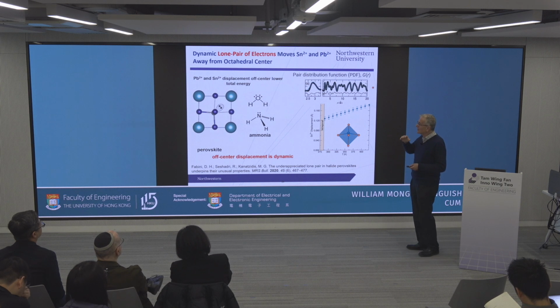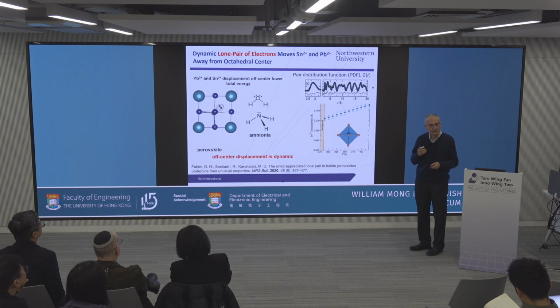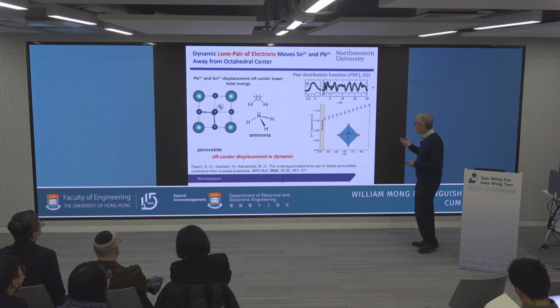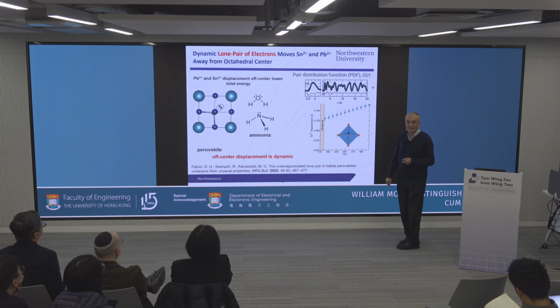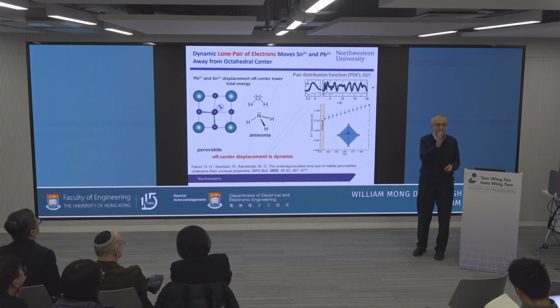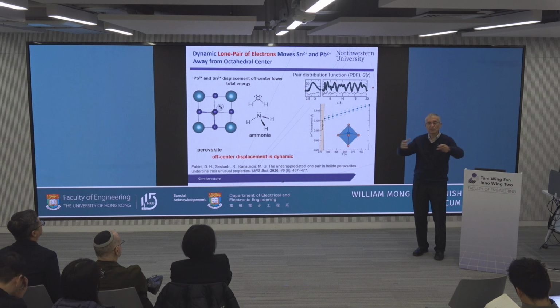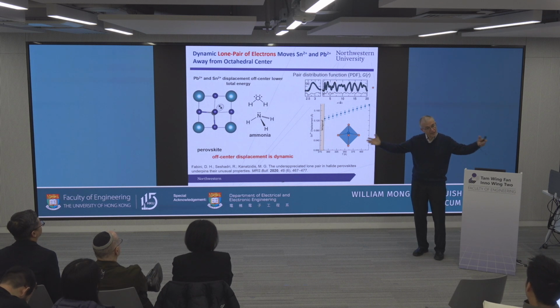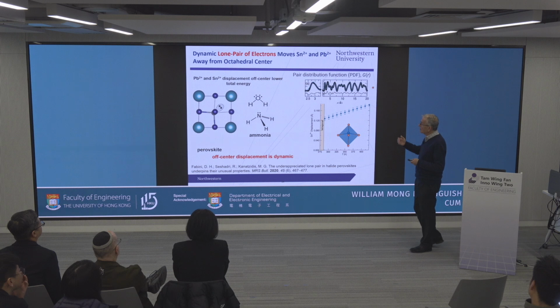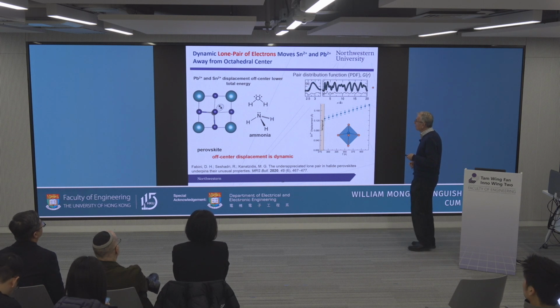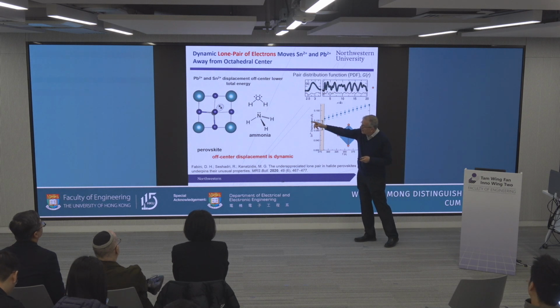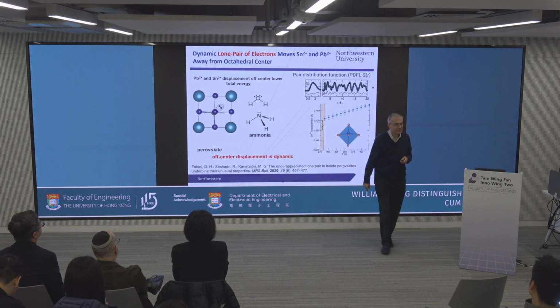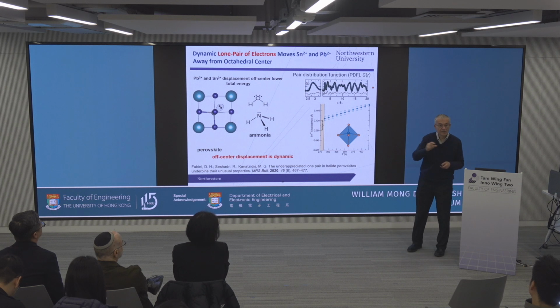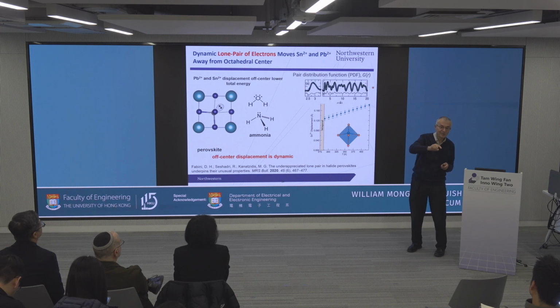And so we said, we need to find another technique that is more local to see the local structure. So there is such a technique. It's called pair distribution function analysis. It's like powder diffraction, but instead of only taking into account the Bragg peaks, you take into account the total scattering, the diffuse scattering, and you analyze all that. And when you do that, then you can find defects that deviate from the periodicity. To fit this data, you need to move the metal atom off-center. Now, you don't see that in crystallography because it's dynamic and it's going in all directions. So it averages out into the center, but the real position is never in the center.